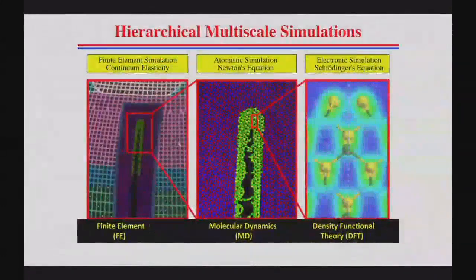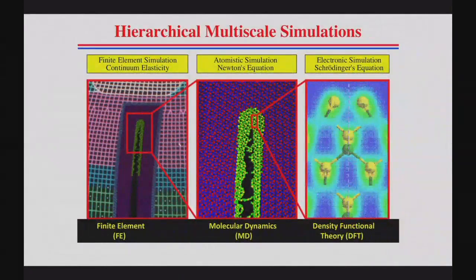So we have also designed an approach, and this goes back 10, 12 years, where we can combine all these different approaches. So for example, if I'm looking at crack propagation in a material, so this one is the crack over here. If I go away from the crack, quite far from the crack, then the displacement of atoms is harmonic, and so one can use finite element far away from the crack. When you come close to the crack, but not sitting where bonds are breaking between atoms, just a little away from here, there are nonlinear strains in the system, and to describe them, we use molecular dynamics. But when you go very, very close to the crack tip, where bonds are breaking, then you have to do quantum mechanics.